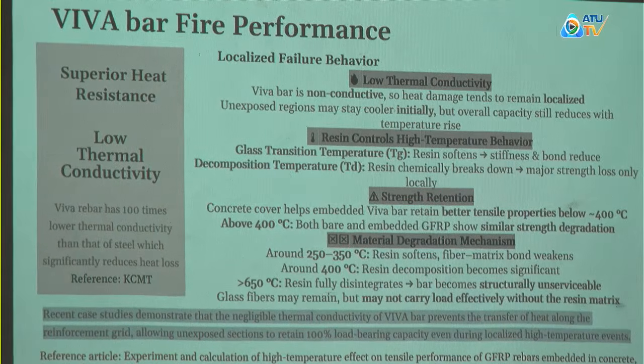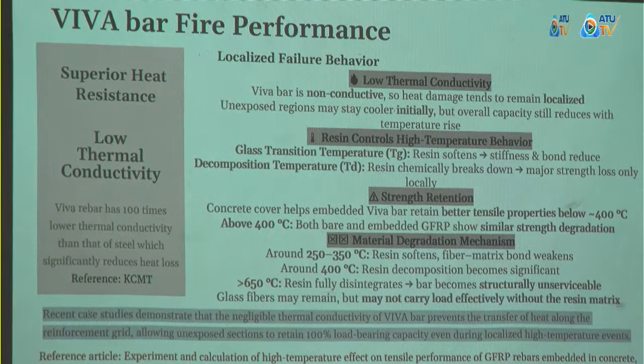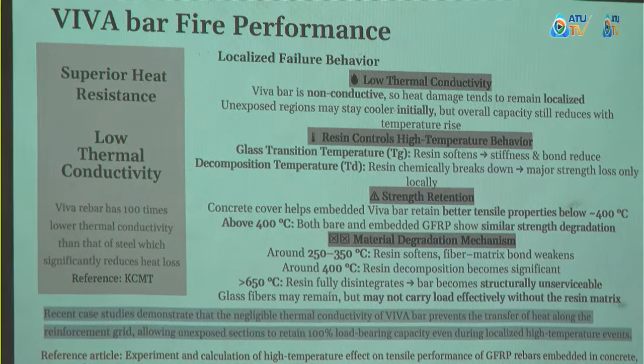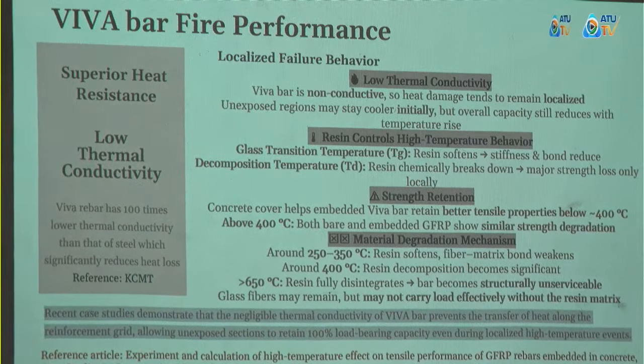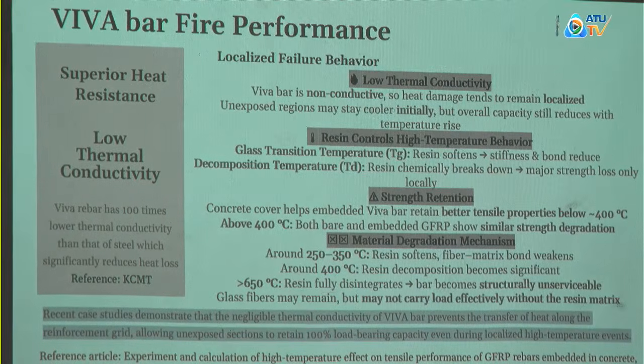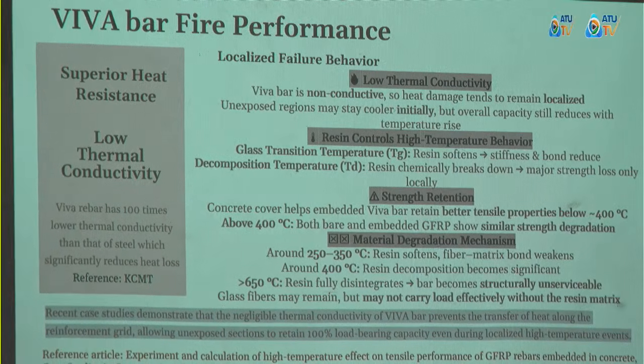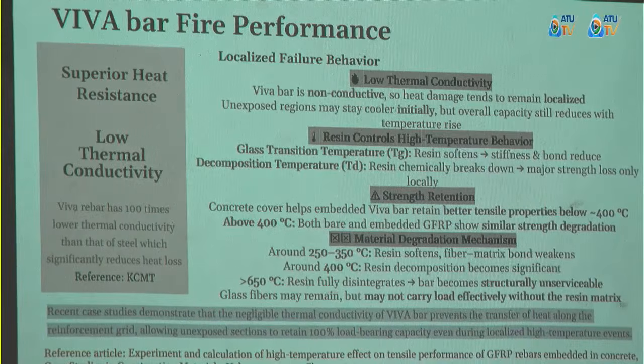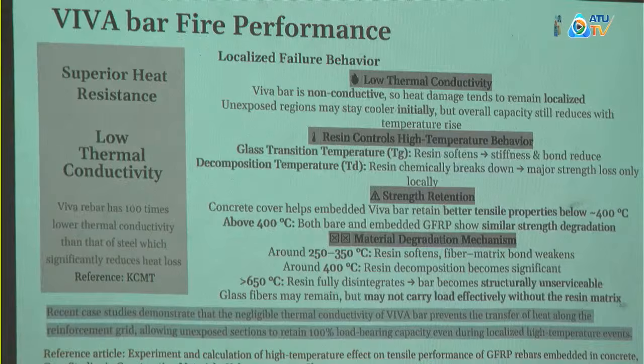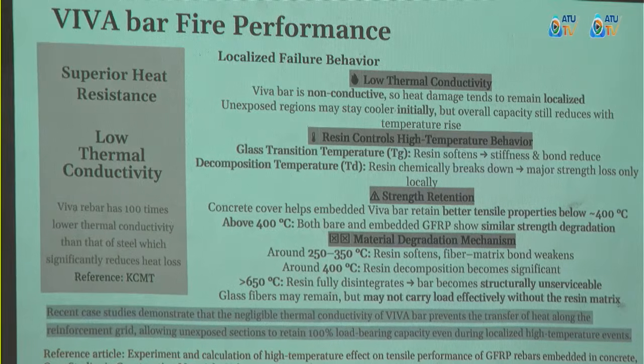Now, moving forward to the Viva fiberglass bar. So unlike steel, the fire behavior of the Viva bar is mainly governed by the resin matrix. This limits, as you can see from the left side of it, the low thermal conductivity, a property that I noticed when doing the article of fire resistance. The Viva bar is 100 times lower in thermal conductivity than steel.